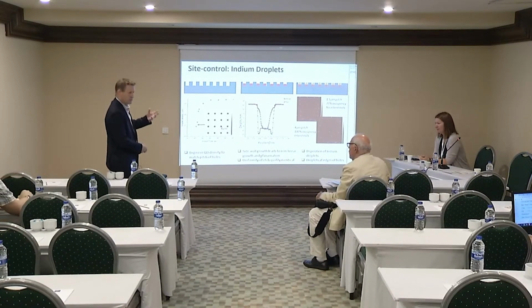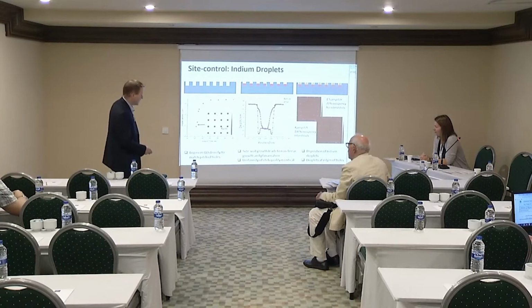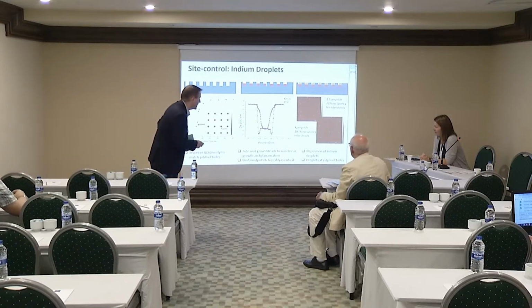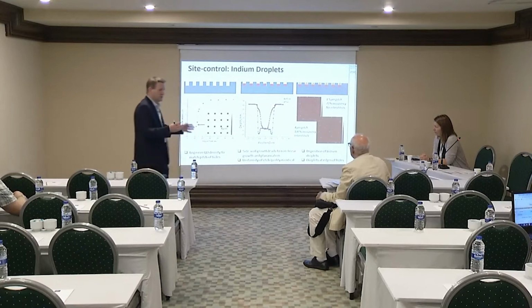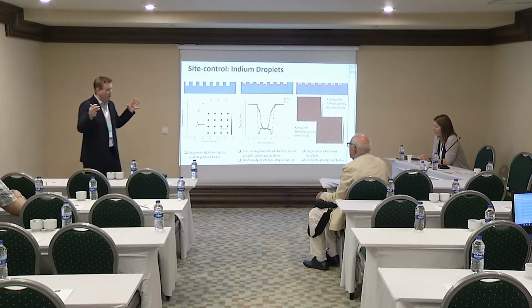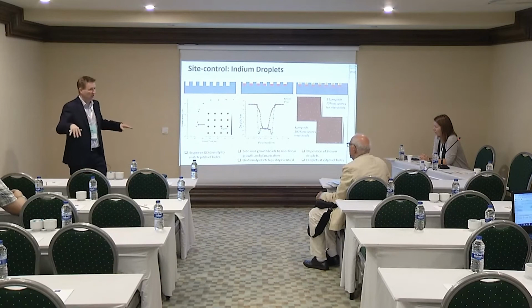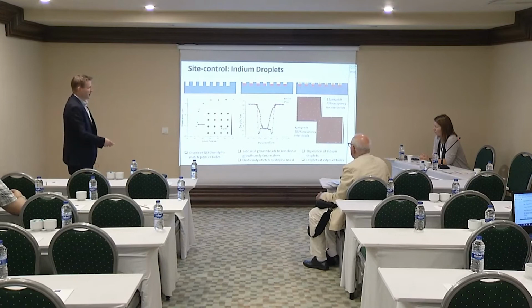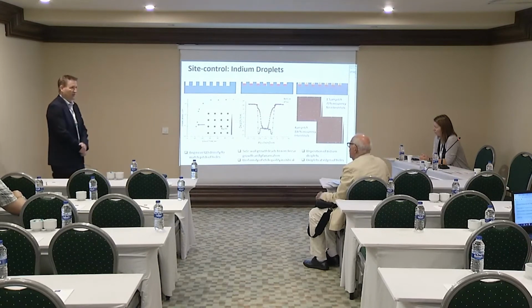But when it comes to investigating this, and also making more advanced circuits, we would go to a smaller pitch. This is actually a 1.5 micron pitch here. We've gone down to even smaller pitches, but that all affects the site control, so it affects the occupancy, because obviously it's related to the diffusion length. But interestingly, even with the large pitch of 4 microns, we get this high occupancy of the holes with the droplet.